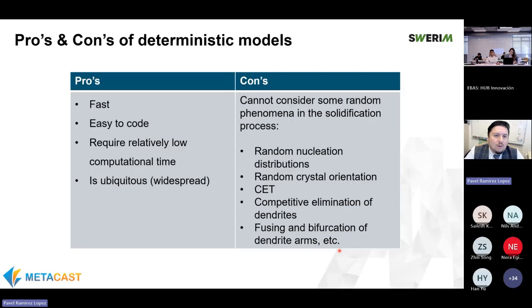As long as we know the heat transfer profile in our casting, it is possible to make a prediction with a deterministic model. And it is very ubiquitous. As you could see, we use it in Fluent very often in our digital twin to predict the solidification. And from there, you can go Scheil type, you can go lever rule, and you can go everything in between. So they can be modified in a more or less rapid way.